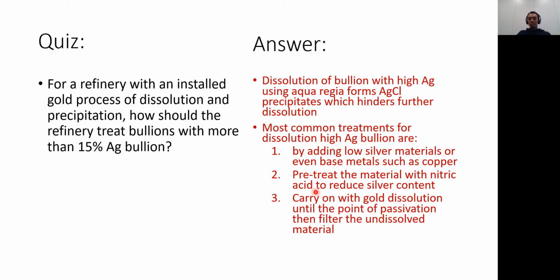So they put unused or unprocessed silver into this bullion to decrease the silver content, so the silver surface on the metal will not hinder the dissolution of gold. The second option is to pre-treat the material with nitric acid. As we know, silver is very soluble in nitric acid. So they will use nitric acid to dissolve silver away from the material, and the gold will stay there because gold cannot really dissolve in nitric acid without any complexing agent. So the silver content will decrease quite a lot, and then they will treat the remaining metals with aqua regia dissolution.